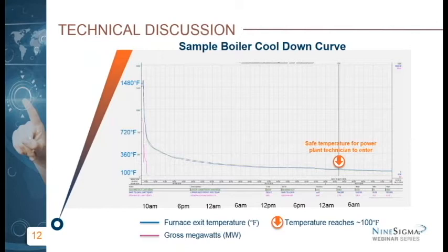A few other points. We did receive some questions about exactly what does an inspection entail. And it's really pretty much a visual look to see, like I said, where the leak is and how extensive the damage is from the leak. Steam at 1,000 degrees and 3,600 pounds is extremely difficult to contain. So it typically cuts through adjacent tubes and, like I said, begins to whip around like a fire hose under those pressures.